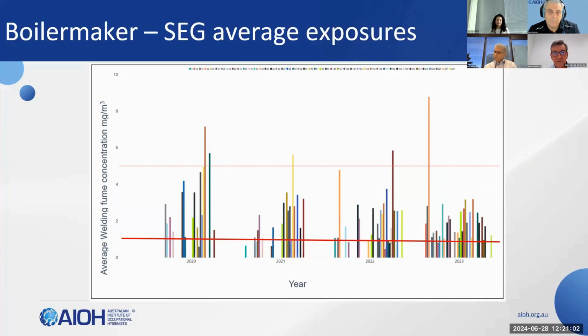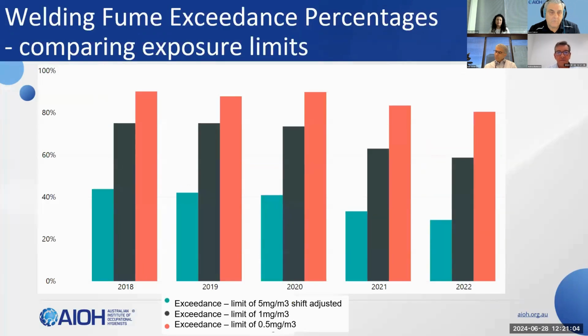This next slide shows what the exceedance rates look like for the same data set. This includes both full shift and task-based samples, ranging from 2018 through to 2022. We see that for the green bars there, 30 to 40% of samples exceed the 5 milligram per cubic metre limit. 60 to 70% exceed the current limit of 1 milligram per cubic metre, which is in black, and 80% exceed the current recommended action limit of 50% of the OEL, which is in red.